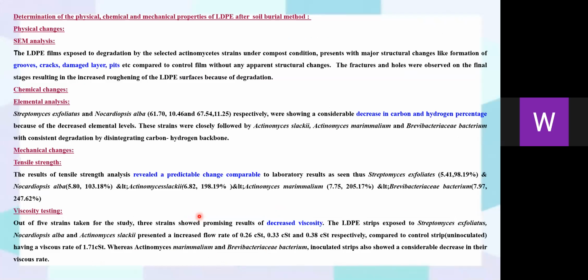SEM analysis. LDPE film exposed to degradation by selected actinomyces strains under compost condition presents major structural changes like formation of grooves, cracks, damaged layers, pits, etc., compared to the control without any apparent structural changes. Fractures and holes were observed at the final stage, resulting in increased roughening of the LDPE surface because of degradation.